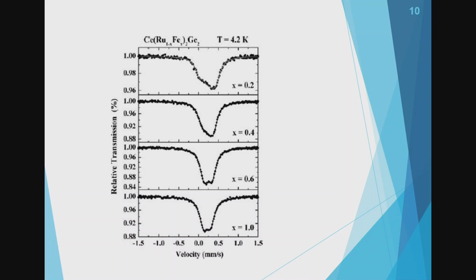So because we had iron in our system, we did some Mossbauer spectroscopy. Just to start this work in Mossbauer, I had never used it, so it was my first attempt. You cannot see it well here because it's an old plot and I could not find the data to fix this, but there is a line here that is fitting this spectra. But in the beginning, we could not understand very well.